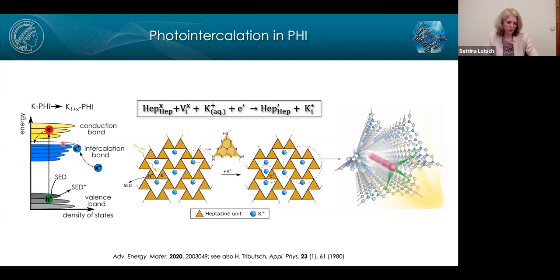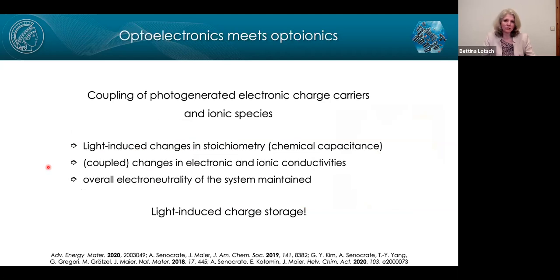And so this, in a sense, we picture as a photointercalation process. We believe that what is formed then is a kind of intercalation band, as we would expect for such intercalation compounds. That is then also responsible for this blue color that we observe. Now, the really interesting question here, which we're currently dealing with, is whether there is a coupling of these photo-generated electronic charge carriers with ions in the system. So in other words, do we see an optoionic effect here?